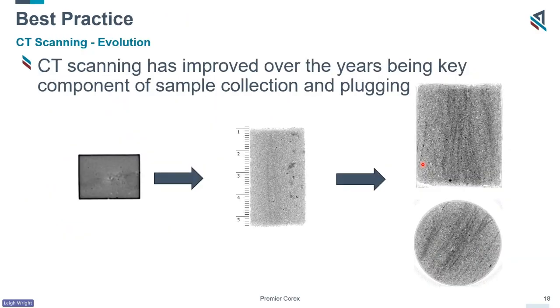So again, we're now a little bit back onto the best practices with the CT scans. Again, this is a core sample from 2015, and to be honest, you can see a small amount of features and some low and high density areas. But looking at the modern CT scans that you get now, you can quite clearly see flow paths, different areas of density, and then on the right-hand side here, you can see that the sample's been plugged with the correct orientation for the maximum flow. So again, just highlighting the evolution and showing the difference that including the CT scanning can make.